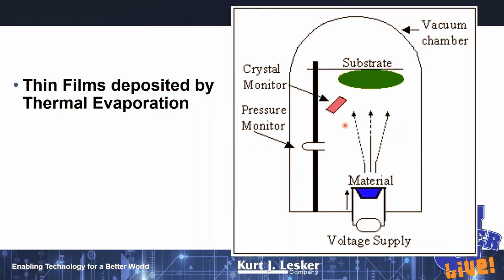You're typically going to have a quartz crystal microbalance, so you can measure deposition rate in real time, and obviously we're going to want to measure pressure. Because if you want to make two films that are identical, they've got to both be done at the same base pressure. If you don't get to that same pressure, you're going to make really horrible films. Again, I'm not showing you the vacuum system that goes along with this.